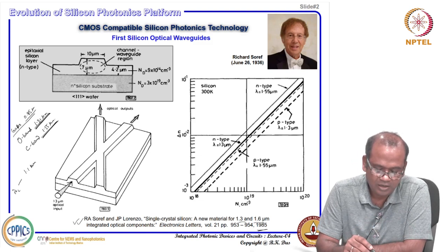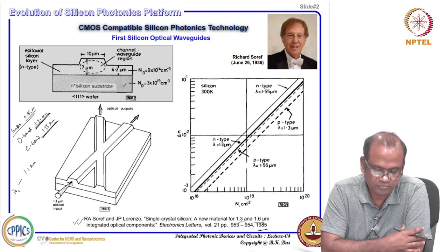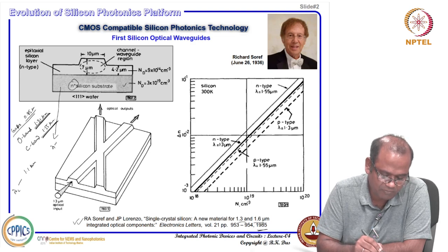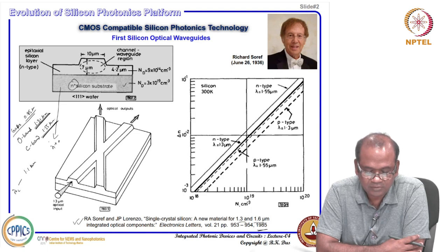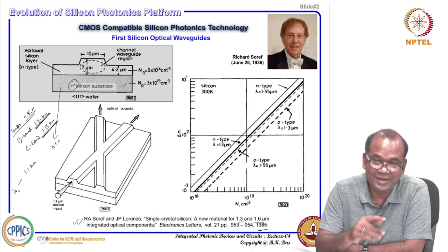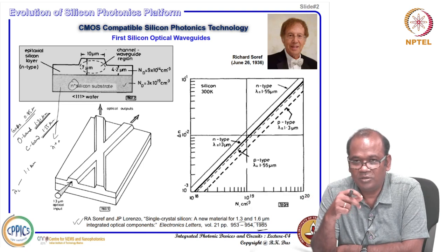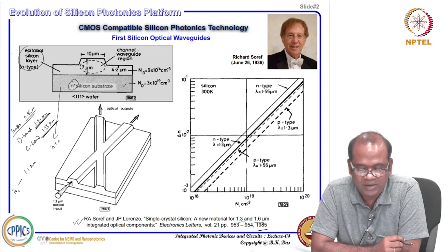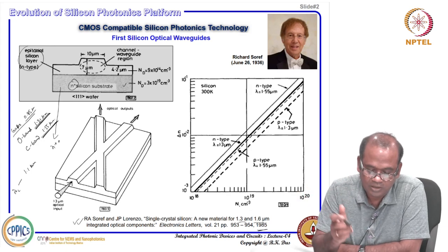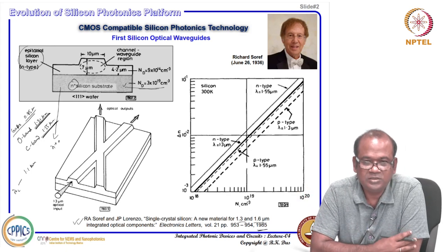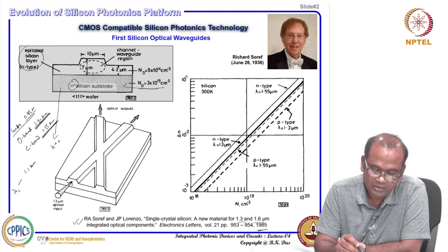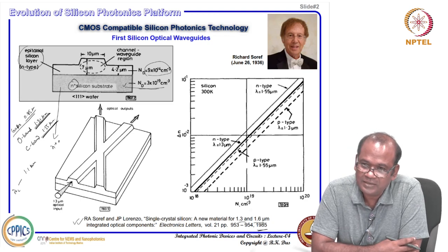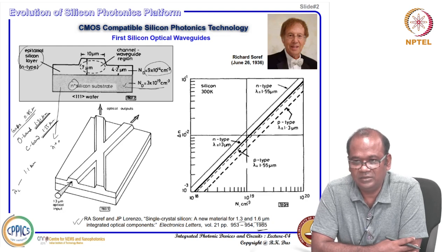How was that done? You take a bulk silicon substrate — crystalline silicon, heavily doped N+, with doping concentration of 3×10¹⁹. Then on top, about a 7 micron epitaxially grown crystalline silicon layer — N-type but not heavily doped, with a doping concentration of about 10¹⁴, much much lower. This can be shown mathematically using the Drude model.